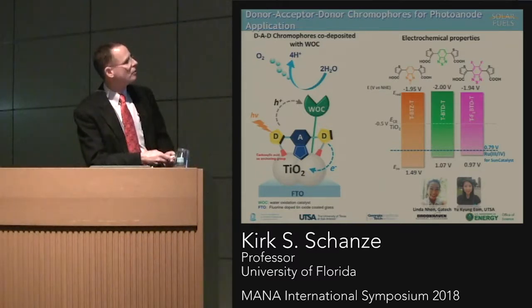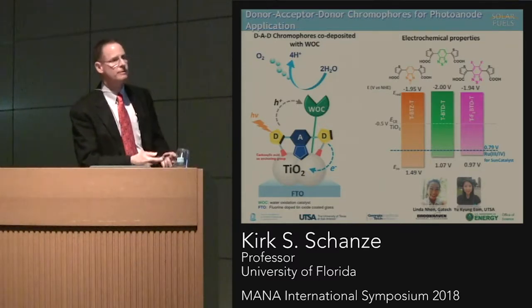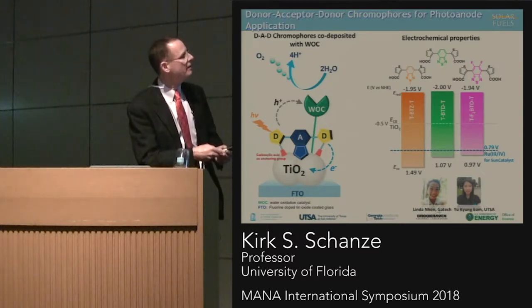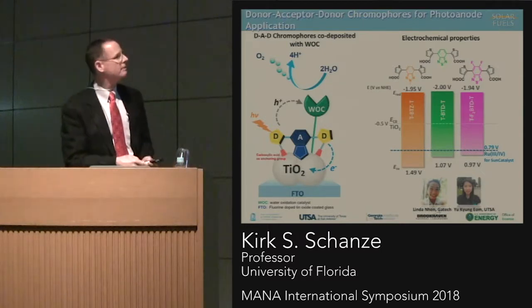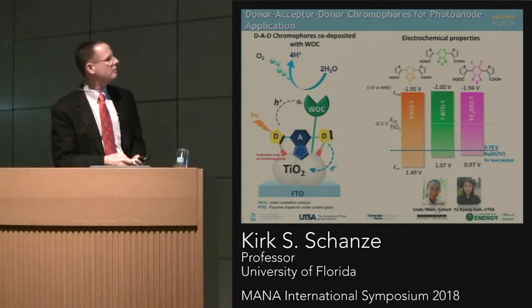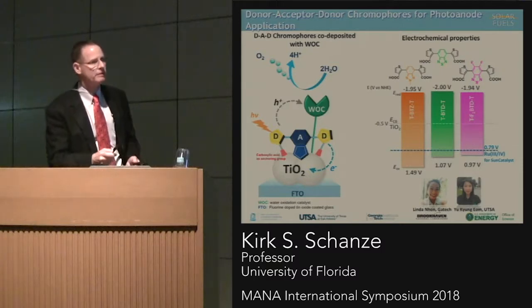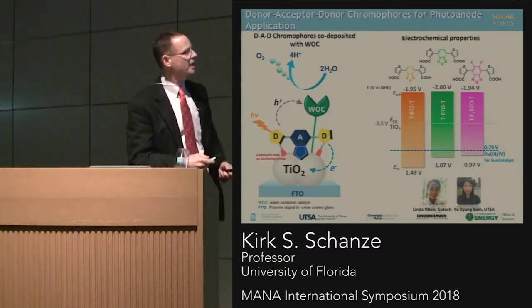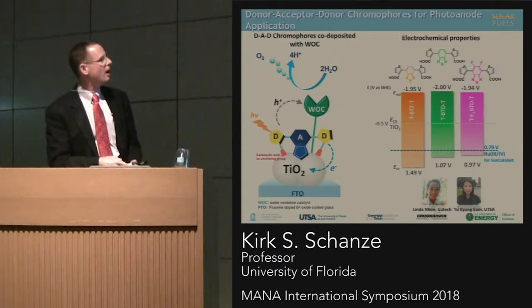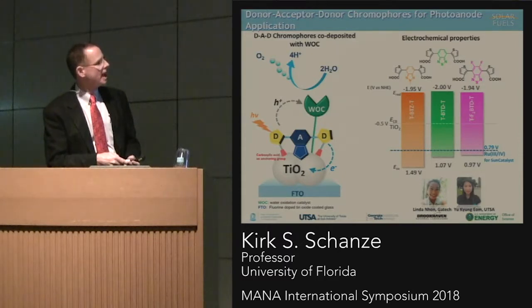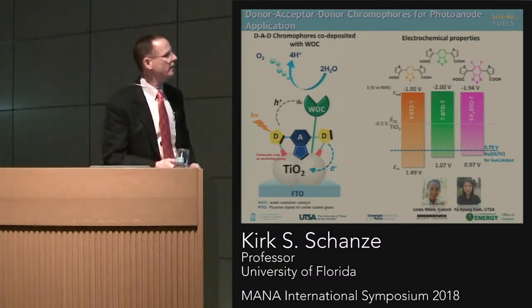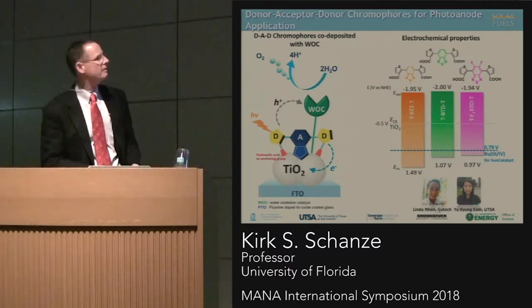These are some of the types of chromophores, and you'll recognize these structures from my earlier discussion. These are again donor-acceptor-donor type dyes that absorb rather strongly in the visible. We study the electrochemistry, so we know essentially the potentials that are needed to do oxidation. This is actually the catalyst oxidation that's required to activate the catalyst, and each one of these dyes, when it's oxidized, is strongly oxidizing enough to turn on the catalyst.